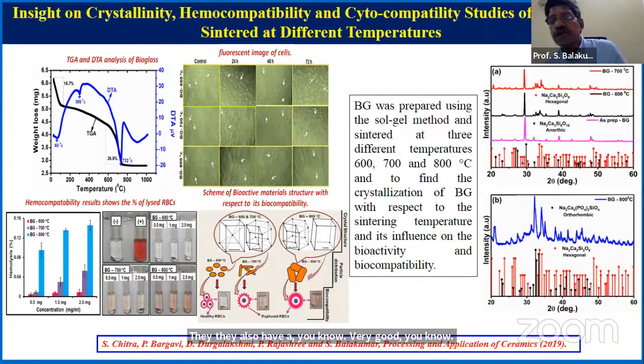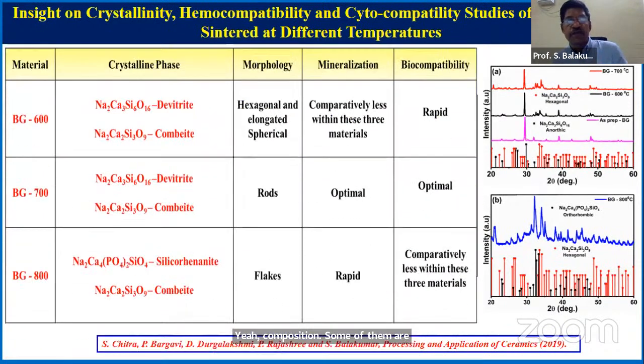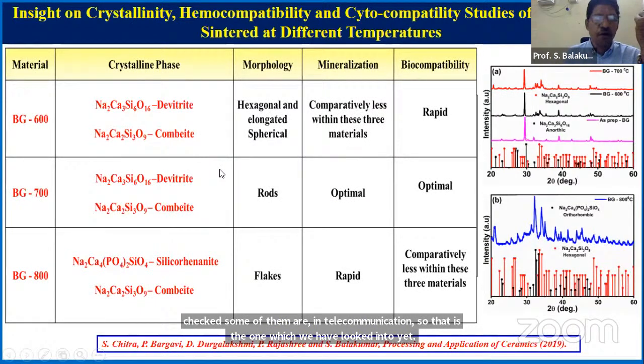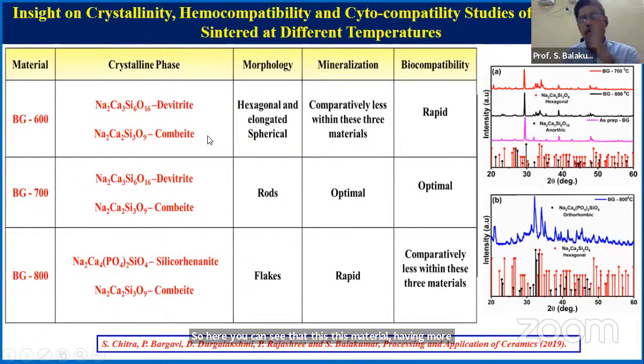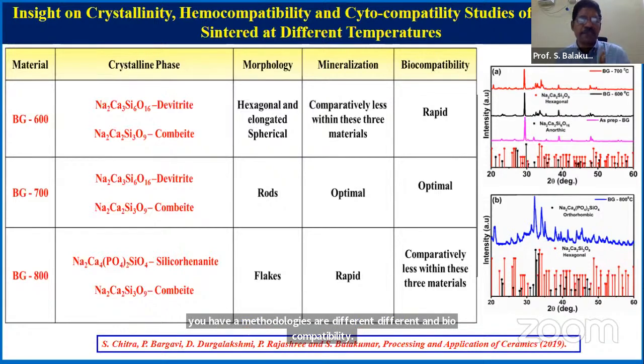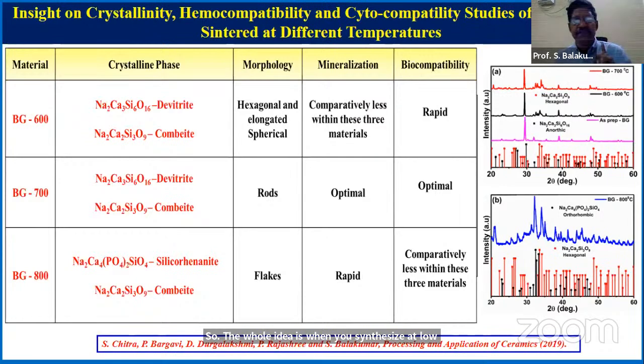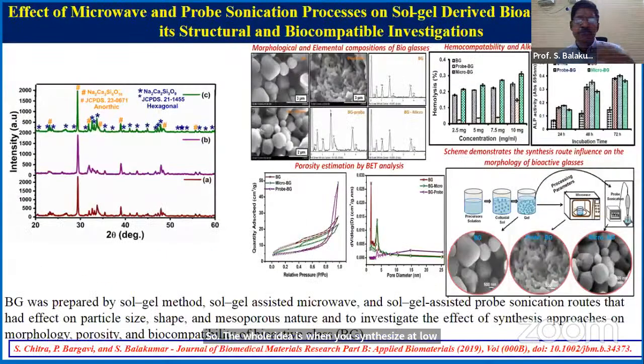But when you look at the structure of the material, there are certain changes. Some of them are in a hexagonal composition, some of them are in a combeite nature, some of them are a silicate with an orthorhombic structure. So that is what we have looked into. Here you can see that these materials have more than one phase. Subsequently, the morphologies are different, mineralization is different, and biocompatibility is different. So the whole idea is, when you synthesize at low temperature, is it possible to have a single phase? That challenge is still there, but I'm just showing some more examples.